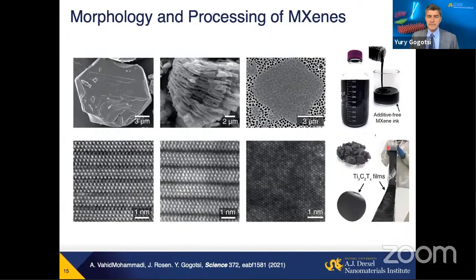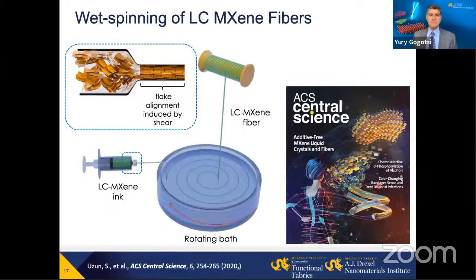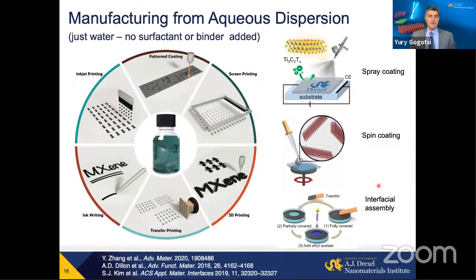choose Dr. blading and produce, without any binders or additives, films which actually have mechanical strength higher than aluminum foil and conductivity of say 15 to 20,000 Siemens per centimeter. So what is important? We can process all these materials just from water, no surfactant or binder added.